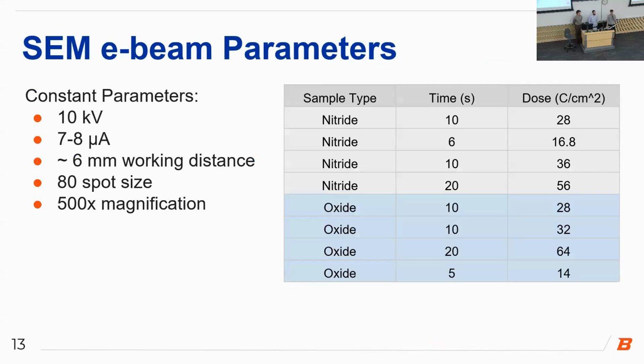Our electron beam parameters were based on dosages that could be encountered by samples through an SEM scan in industry. And our dosages went from 14 coulombs per centimeter squared to 64 coulombs per centimeter squared. It is important to note that the SEM that we were working with did not have a Faraday cup, so we use the emission current of the SEM to estimate these dosages.